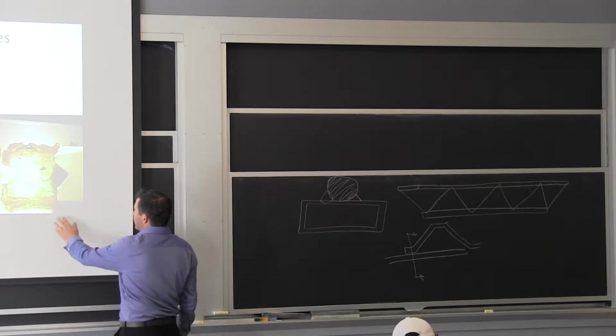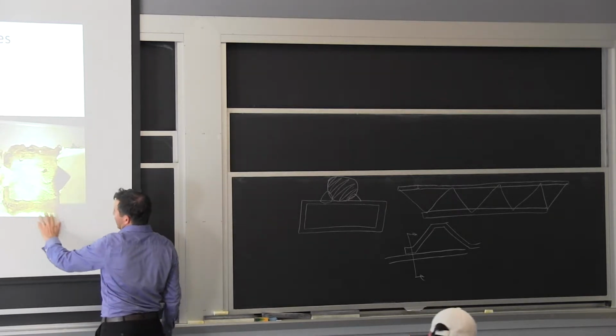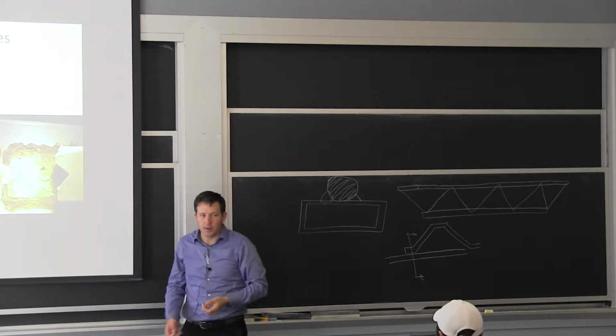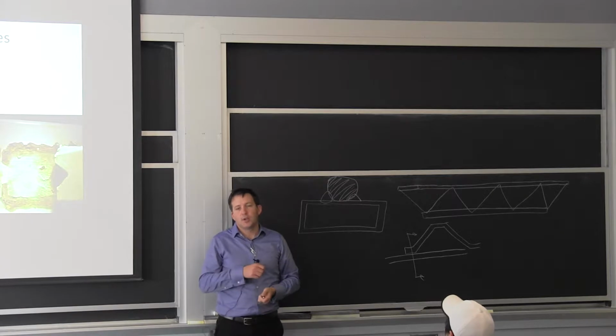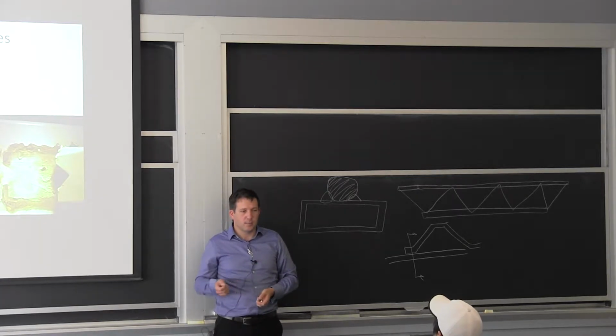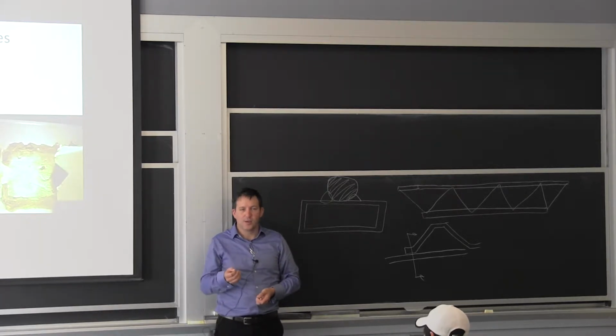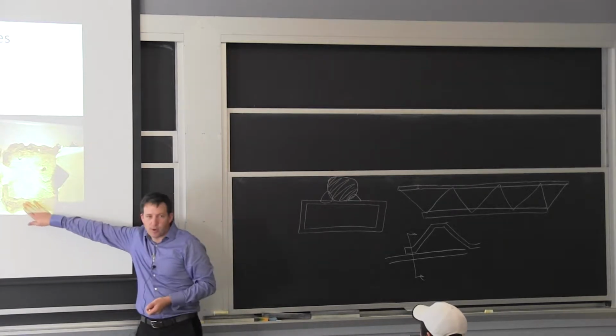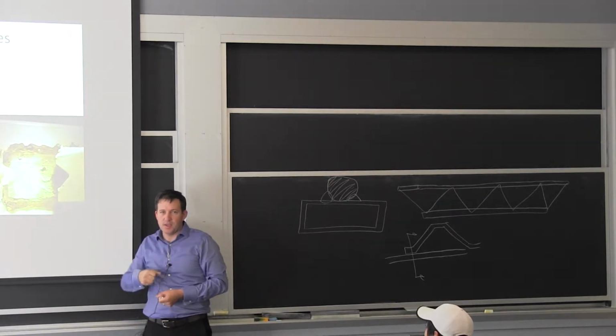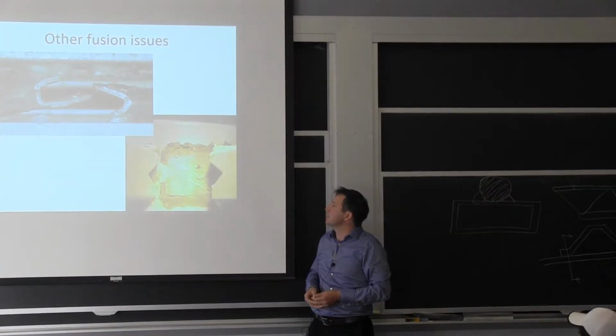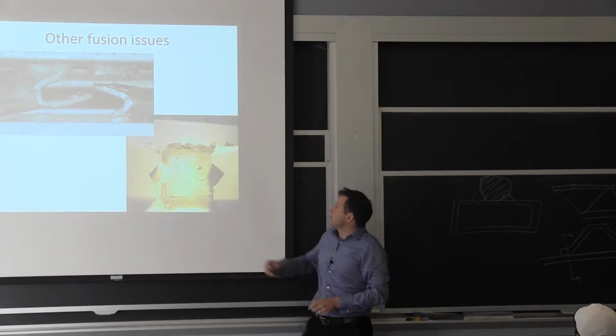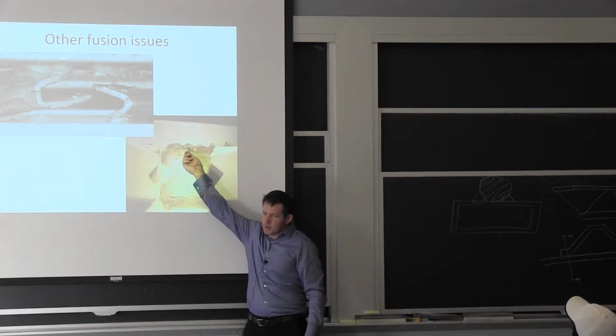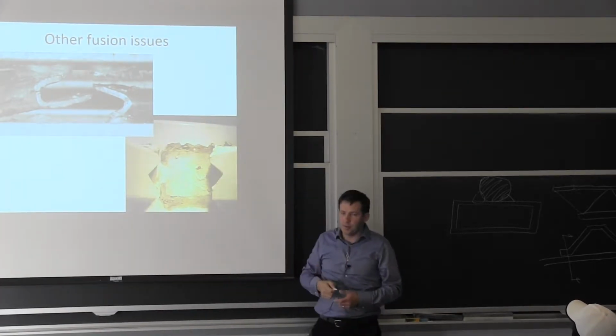And what you can see at the bottom here is, again, original surface from the mill of the steel. So you came and you had a deposit, but it just never really fused this bar, and therefore it's very easy to pull it down after the fact. There's a little bit of fusion here. You see it took a bite out of the member.